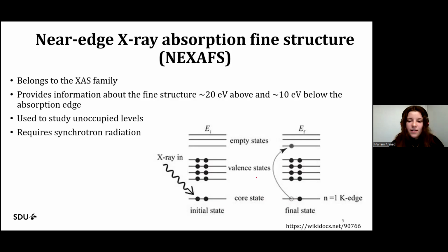So therefore, the emitted electrons cannot leave the material, but instead they will be excited to an unoccupied level. This means that NEXAFS can give us information about unoccupied levels in the material, while XPS only provides information about occupied levels such as core levels and valence bands.